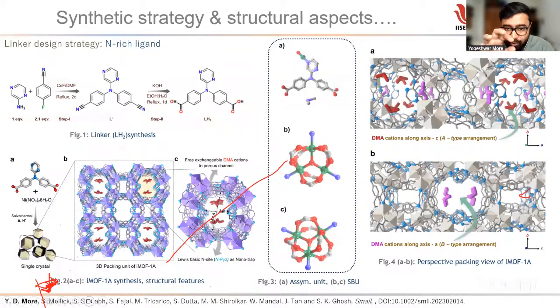It is highly selective for uranyl-type cation geometries. So the pore is selective for the uranyl cations, and the ionic nature allows the ions to go out and uranium to sit on the pore surface. And this Lewis basic nitrogen forms the coordination geometry, which is particularly an anchoring geometry for uranium. It does not anchor other components like sodium and calcium. So this morphology and its chemical functionality within the pore decide the fate of uranium adsorption, and it makes it a standout adsorbent.